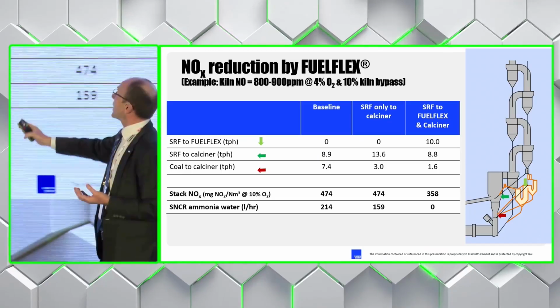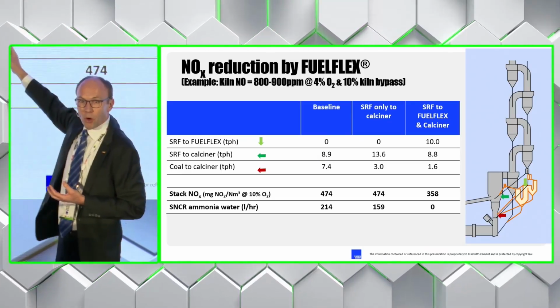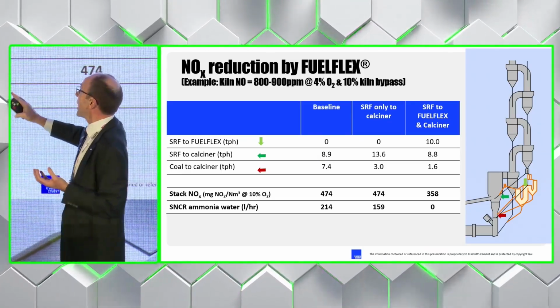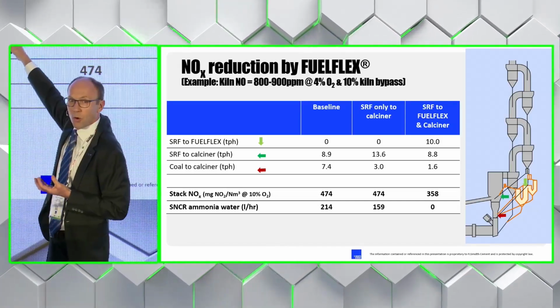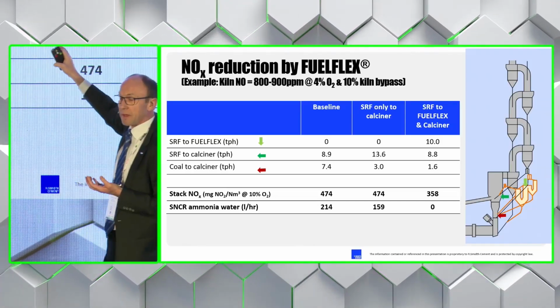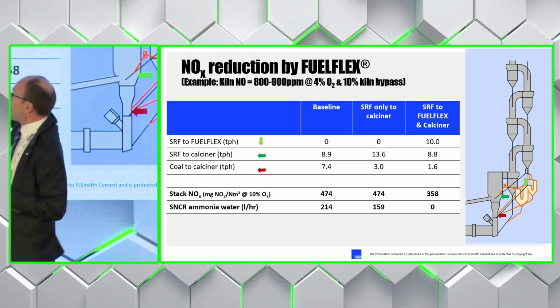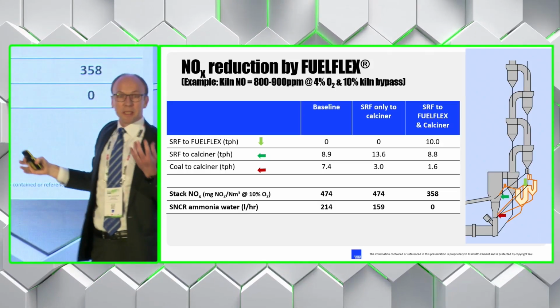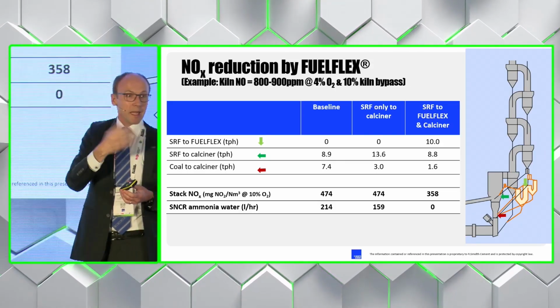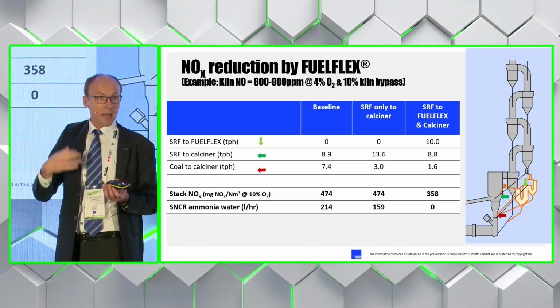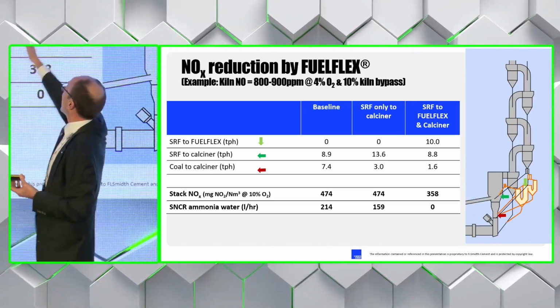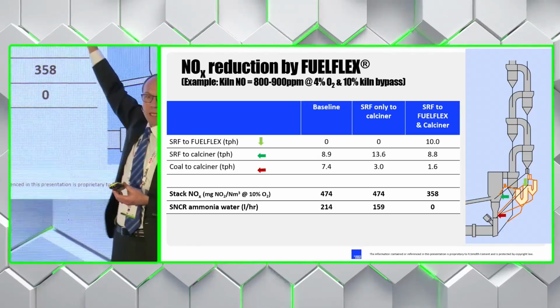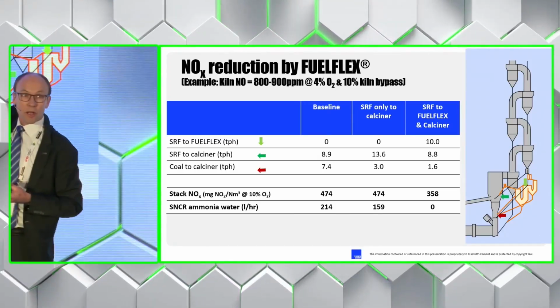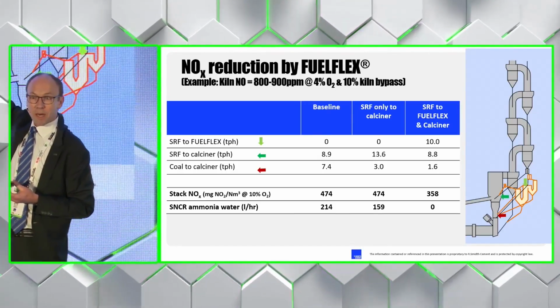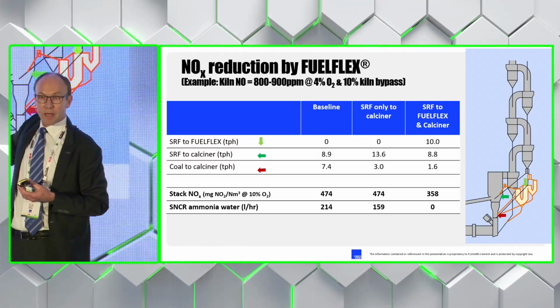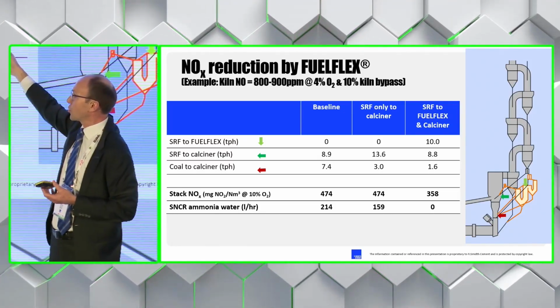Over here, I put in as the baseline. That was basically before we installed the FUELFLEX Pyrolyzer. You have about 50% coal and 50% alternative fuel in the calciner. The second line here is the situation where you put about 80% alternative fuels fired directly in the calciner. And the third column here, we have 10 tons an hour of solid recovered fuel going into the FUELFLEX Pyrolyzer, and the rest going into the calciner. Here we have 90% substitution.